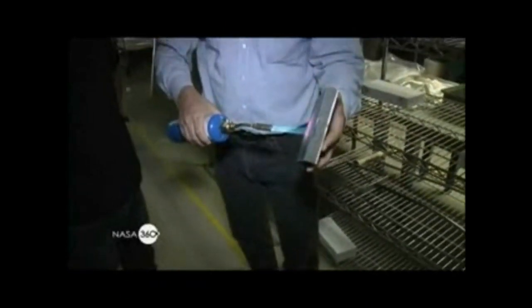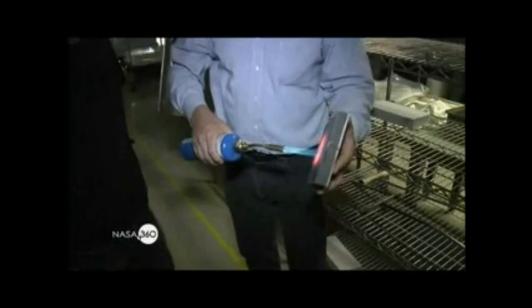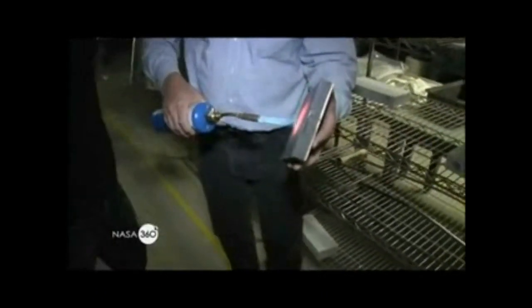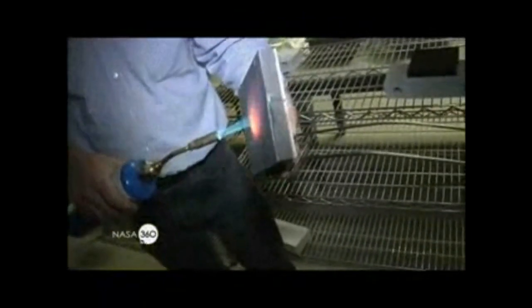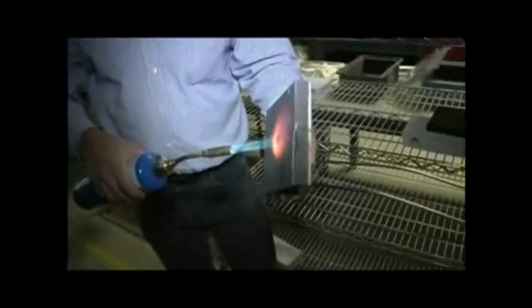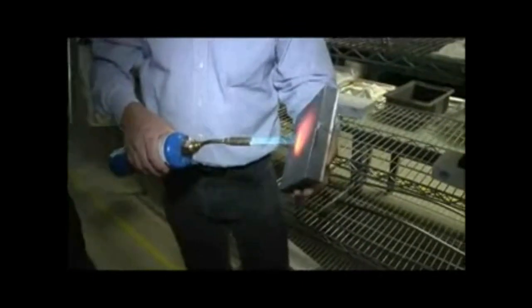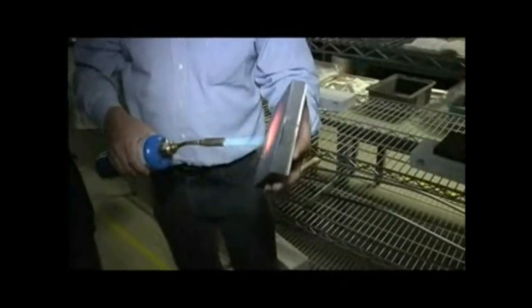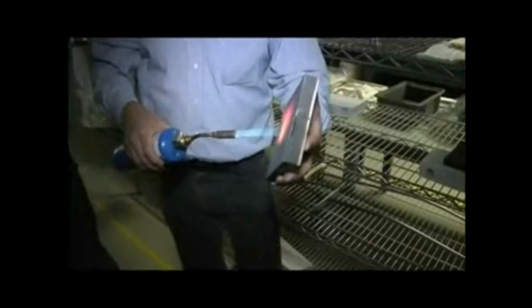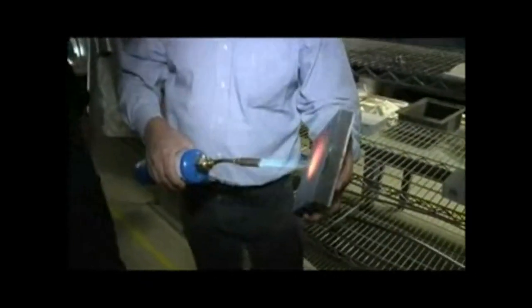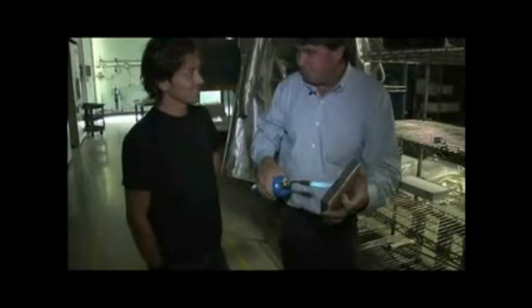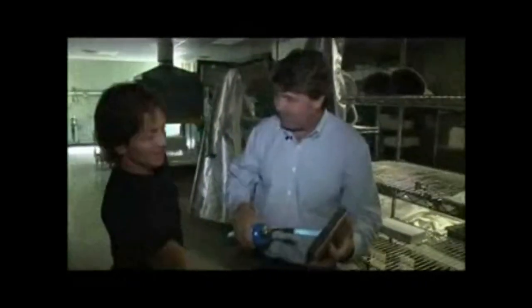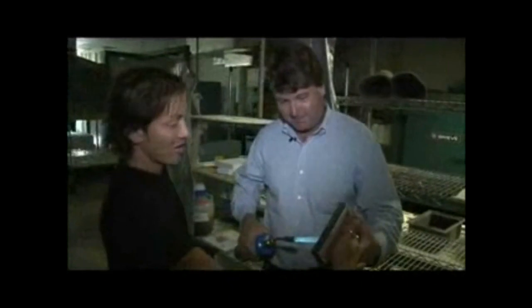And I can actually take this tile and heat it up with a blowtorch, and you can see quite rapidly the surface will get up to about a little over 2,000 degrees with just this propane torch. But the actual heat is soaking through the tile very, very slowly. I could stand here for probably around 20 minutes before the back of the tile becomes uncomfortably hot and I'd have to put it down. Really? It's not hot now? On the other side? No, it's not hot at all. I've got my finger right on the back side of it and I can't feel anything. It's probably going to take about 7 or 8 minutes before it starts to warm up. So yes, you can put your finger on the back of it. Yeah, it's just nothing.